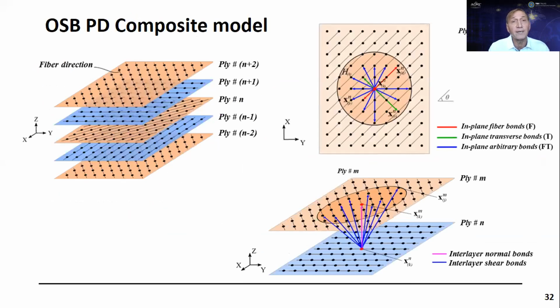So I'm not going to go into the details of how we come up with the peridynamic model for composites, but it's pretty much the same as what I described. We have the ordinary state-based composite model. The only difference is that we distinguish the peridynamic parameters in the fiber direction, in the transverse direction, and in the arbitrary directions. Additional parameters. And also, this is within the ply, but also between the plies, we have the interlayer normal bonds and interlayer shear bonds. So we determine all of these bond constants in terms of the engineering constants that we know for a given ply.